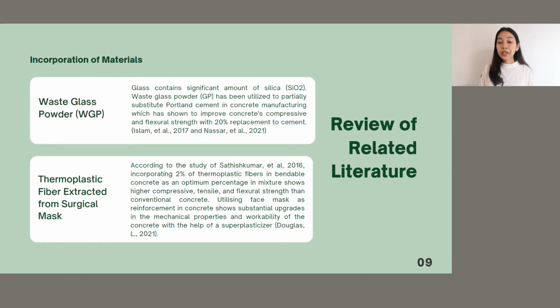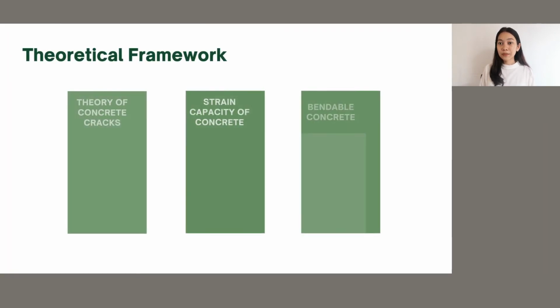2017, highest compressive strength and flexural strength is achieved at 20% optimum replacement of waste glass powder to cement. Moreover, ECCs are often reinforced with short fibers and micromechanically designed to have high tensile ductility and repeated cracking according to Kin et al. 2020. Douglas, L., 2021 suggested that utilizing face mask as reinforcement in concrete shows substantial upgrades in the mechanical property and workability of the concrete with the help of a superplasticizer.